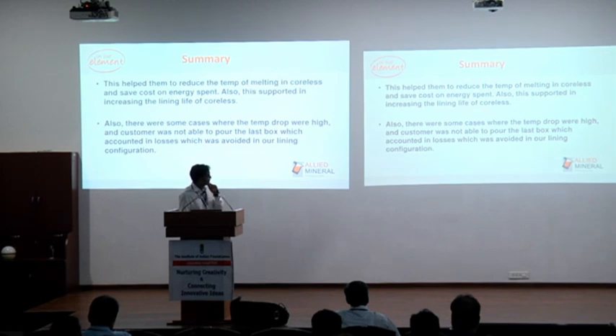So this helped in reducing the temperature of the metal in the coreless furnace and saved cost on energy spent. Obviously, whenever you require high temperature, you take high temperature from the coreless furnace, and that impacts the main working lining. Since we were able to control the heat losses, they were able to control the temperature in the coreless furnace for tapping out the liquid metal, and the lining life was also increased, and the energy spent was also reduced. And there are some cases where we have experienced that because of the low temperature, the last box can't be poured, and in this case that was reduced.